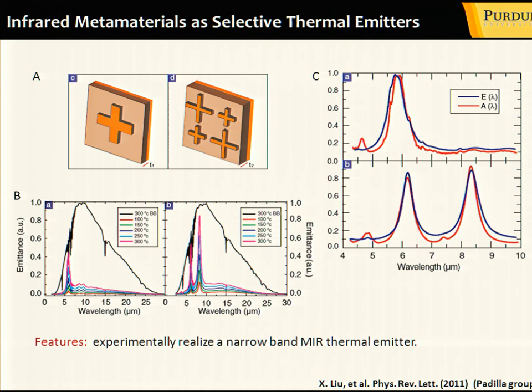Also, quite an interesting development, in my opinion. Well, with metamaterials, you could also control the very basic things related to blackbody radiation, and specifically, you could control the properties of thermal emitters. In this particular case, you have metallic structures, sort of metamaterial structures, where you could exactly control the frequency where electrical and magnetic resonances occur. You could, for example, make it so that there is only one resonance or two resonances for these two different structures shown in the pictures. And in thermal equilibrium, of course, according to Kirchhoff's law, emission should just be equal to absorption. And therefore, emission occurs at particular wavelengths: for this structure just at this one resonant frequency, and for this one at these two frequencies.